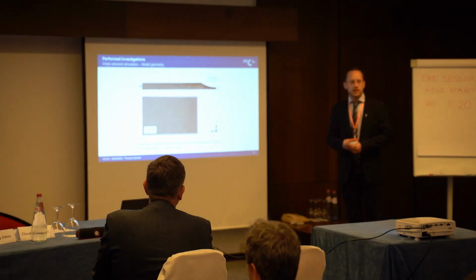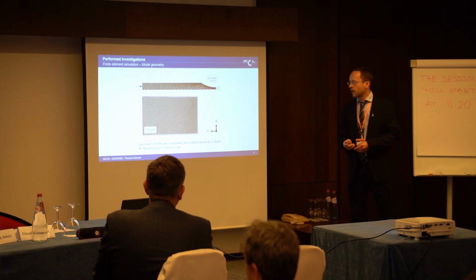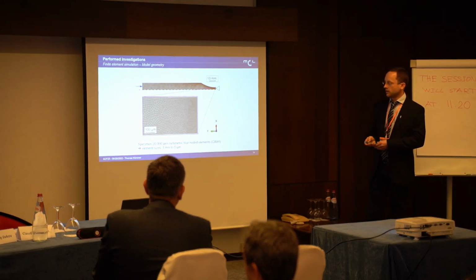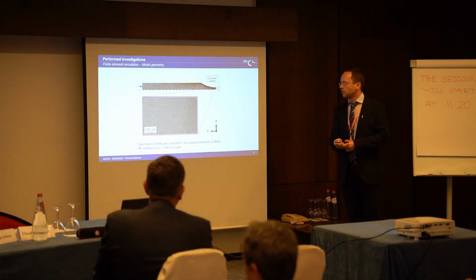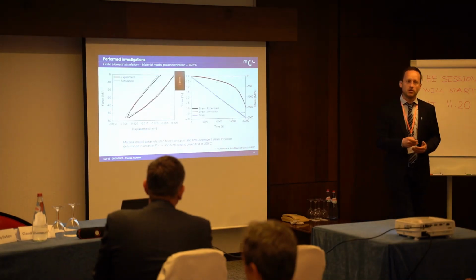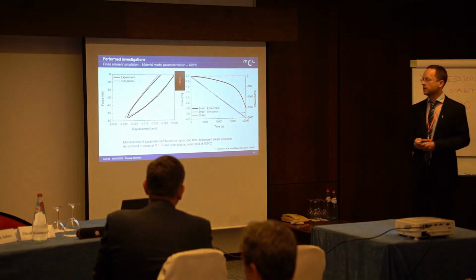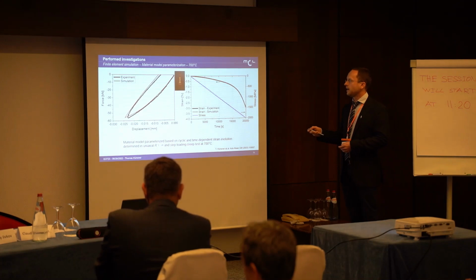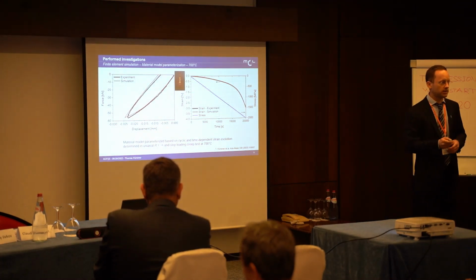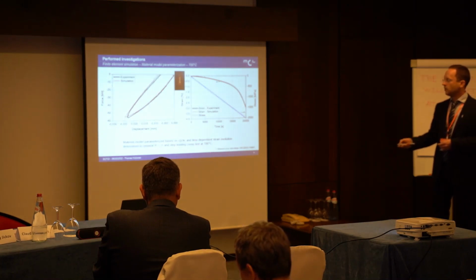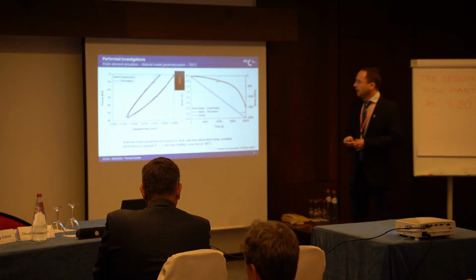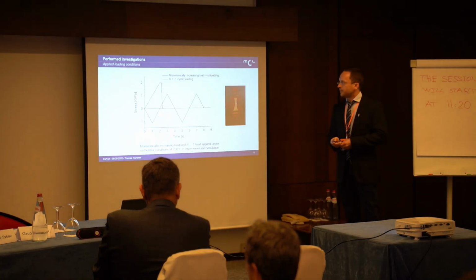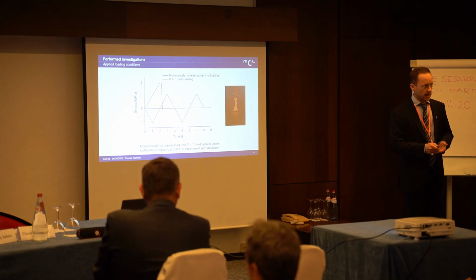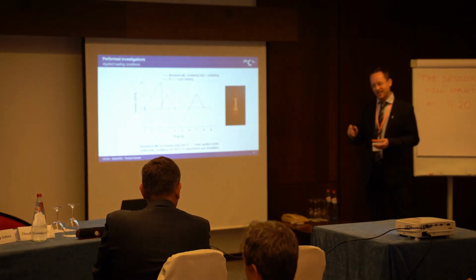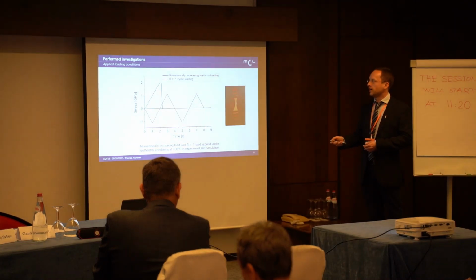We also did FEM modeling of our specimen to understand its loading rather well. We did that with these conditions here. You can find those details in the paper, as I'll point out to you later. We parameterized the material models we applied to understand the deformation behavior of our specimen using cyclic experiments and creep experiments with a stepwise increased loading fashion, all at 700 degrees C, as pointed out with this image. What we applied was R-1 loading and monotonically increasing load. We did that until fracture, and we also performed stop experiments to look at the microstructure before fracture.